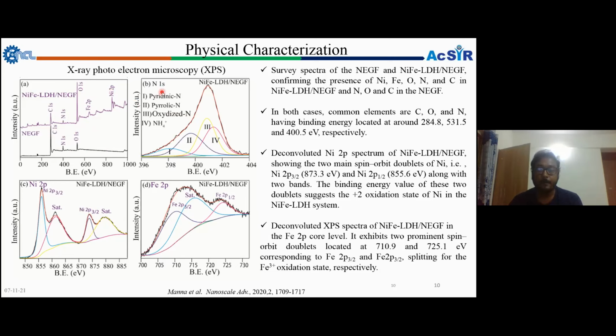As I told in the introduction slide, nitrogen could be doped over the graphene substrate in various forms like pyridinic, pyrrolic, or oxidized forms. Here also the deconvoluted spectra suggest that four different kinds of nitrogen are present. Importantly, as we are heat treating at a low temperature of 180 degrees, there is no possibility of graphitic nitrogen formation. This is a very important thing, because graphitic nitrogen participates in electronic conductivity as well as durability. So at low temperature, when you are heat treating, there is no chance of graphitic nitrogen formation, and that is very much beneficial for better stability.